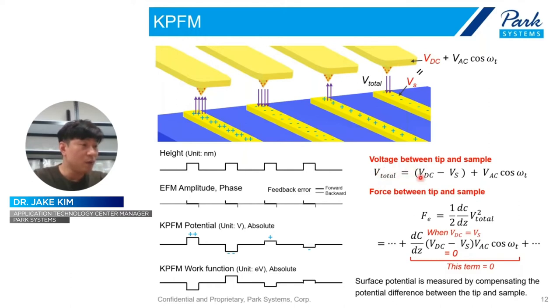Okay, here, the total voltage between tip and sample can be described like this. Here, VDC means the DC bias we applied, and VS means the surface potential, and electrostatic force also can be expressed like this. Just simply speaking, in EFM, we just collect the whole signal of this distance. But in KPFM, the system applies the DC bias to make the zero value of this term. It means if we can track this DC bias, it is the surface potential, because the DC bias makes the zero value, so the DC bias will be the same as this surface potential.